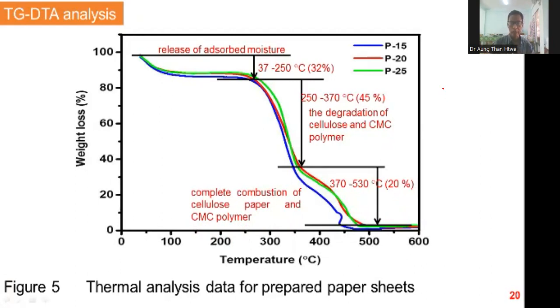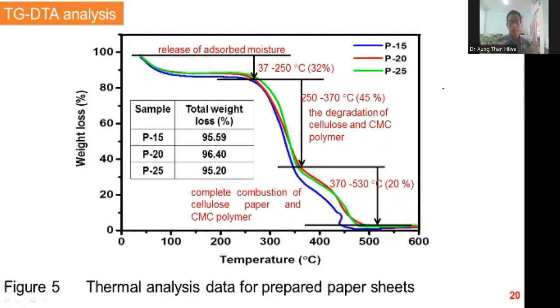This is due to the complete combustion of cellulose paper and CMC polymer. This is how the thermal degradation nature was observed. The total weight loss of the investigation for P-15 is 95.59%. P-20 paper is 96.40% weight loss, and P-25 is 95.20%. According to the data, P-20 paper was observed to have the highest weight loss percent.